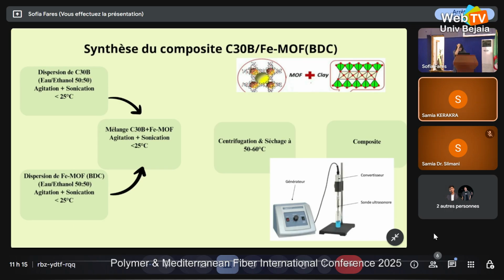Then both solutions were added to each other, and the mixture was centrifuged to remove solvents, then dried at 50 degrees Celsius for 12 hours to obtain our composite powder.